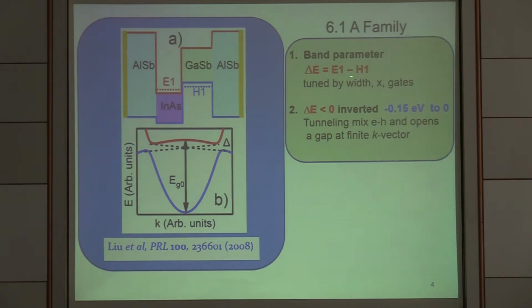So if you look at the parameters for those materials, you can change this from inverted to non-inverted by changing the thickness of the material or by gating. And if you are in the inverted range, you have a 150 milli-eV range to be tuned.